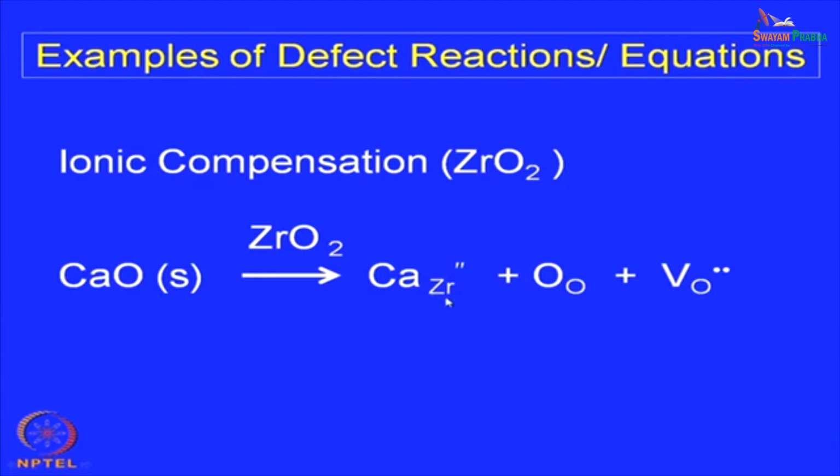This was tetravalent and this is divalent. So, there is a deficiency of 2 positive charges. Now, this charge has to be balanced, then only calcium can go into the solid solution, right. Otherwise, if the charge cannot be balanced, then it cannot go into the solid solution, it cannot form a solid solution. Fortunately, the charge has been balanced in this fashion.